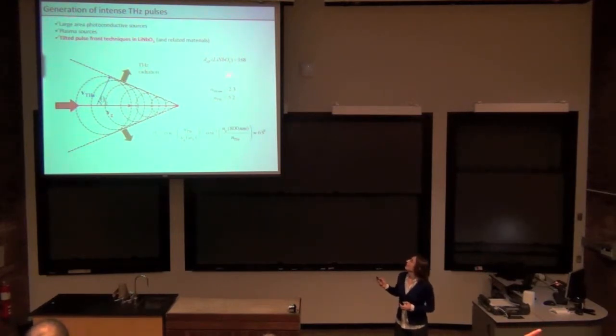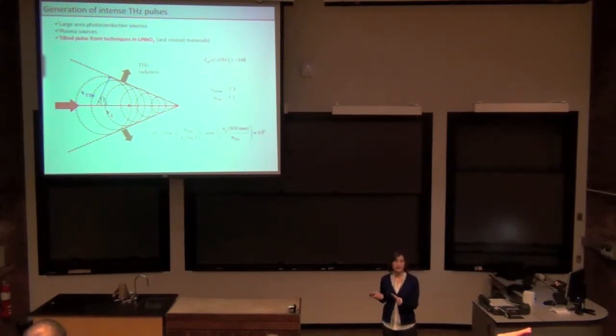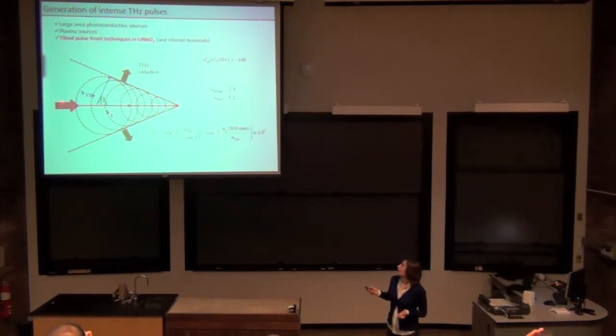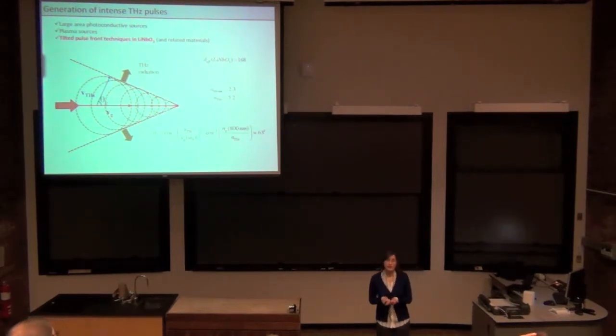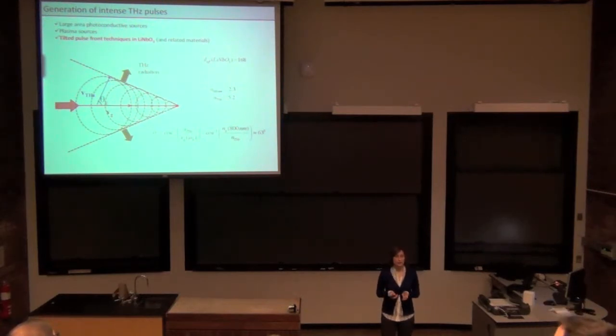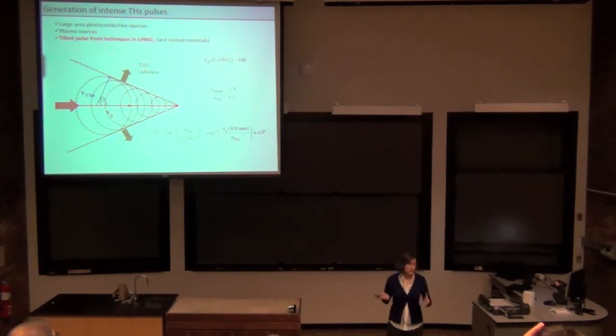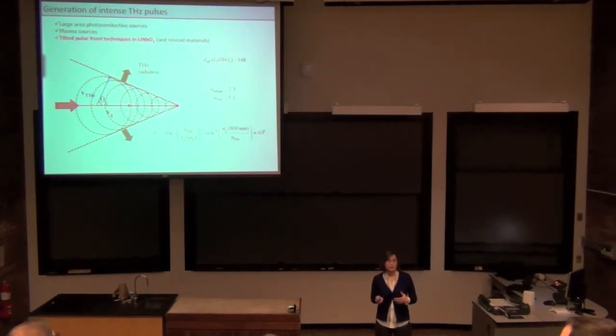The refractive index is very different for 800 nanometers, which is what we use to generate terahertz pulses, and the terahertz wave itself. This is what would happen as you propagate this terahertz pulse and the 800 nanometer pulse... velocities. That process is very efficient because now we have very long interaction lengths.